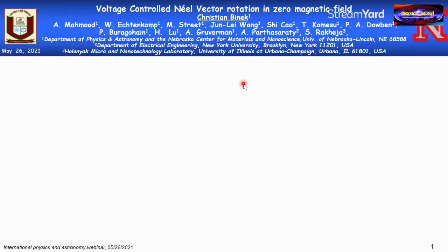I have worked on this for a long time and use so-called magnetoelectric materials to do that, and I will say a few more words about this. But one catch has always been that if I want to take a particular textbook magnetoelectric material and switch its antiferromagnetic spin structure from one orientation to the other, I have to have a magnetic field present. That is because the magnetic field breaks time inversion symmetry. Switching an order parameter that is odd under time inversion with a field that is odd under time inversion is not straightforward. So I always needed a magnetic field.